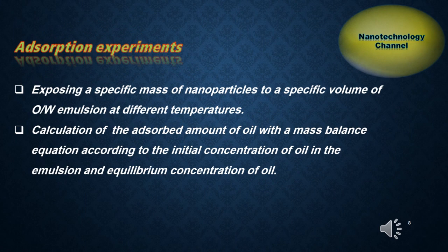The next step is measuring the ability of the prepared nanoparticles to absorb oil spills by exposing a specific mass of nanoparticles to a specific volume of oil-in-water emulsion at different temperatures, and then calculating the adsorbed amount of oil using a mass balance equation according to the initial concentration of oil in the emulsion and the equilibrium concentration of oil.